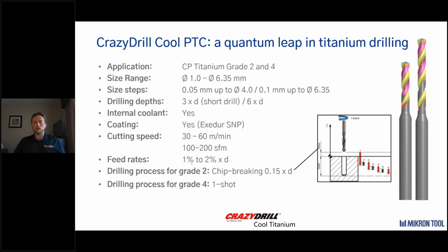Where we get into the effectiveness and where I would apply LFV or HFT in an effective way would be a chip break cycle. As we see here, the process for grade 2 and grade 4 in some circumstances, we do have a necessity to actually break a chip. As stated before, grade 2, that pure titanium, is much more gummy. It really doesn't like to break a chip. It doesn't like to be controlled. So as we bend over the chip with a cutting edge, we need to actually remove ourselves from the cut to cause that chip breakage.